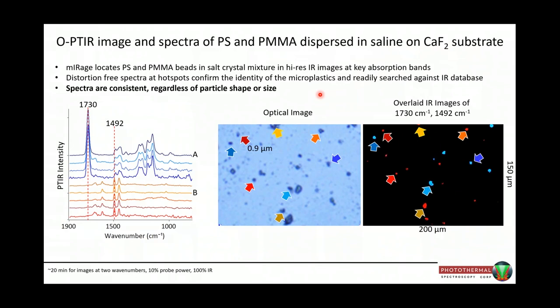And the particles are various shapes and sizes, yet the infrared spectra we get out don't change depending on the size. And some of these materials are salt, which don't have an infrared spectrum, which would cause all kinds of problems in a normal FTIR measurement. We can easily get in there, and regardless of the size of the particle, get a great chemical ID of the material, and we can collect images where we tune to a single wave number and light up which particles are the PMMA and which particles are the polystyrene.